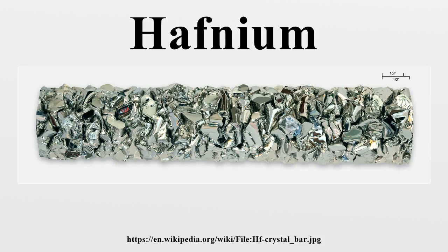Alloys. Hafnium is used in alloys with iron, titanium, niobium, tantalum, and other metals. An alloy used for liquid rocket thruster nozzles, for example the main engine of the Apollo lunar modules, is C-103, which consists of 89% niobium, 10% hafnium and 1% titanium. Small additions of hafnium increase the adherence of protective oxide scales on nickel-based alloys. It improves thereby the corrosion resistance, especially under cyclic temperature conditions that tend to break oxide scales by inducing thermal stresses between the bulk material and the oxide layer.